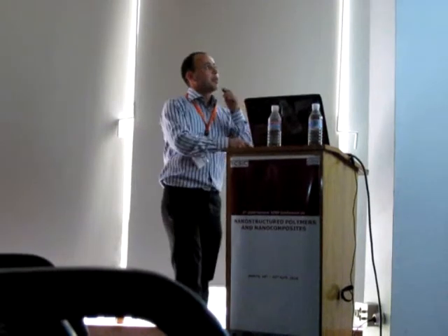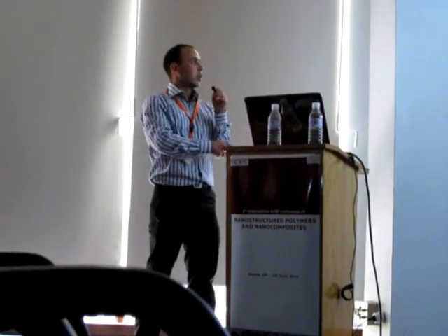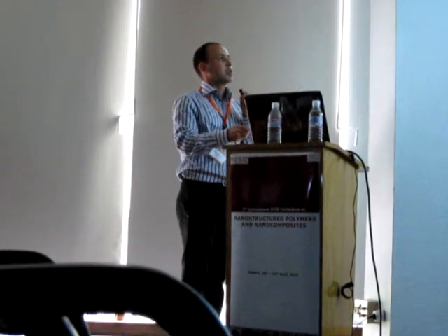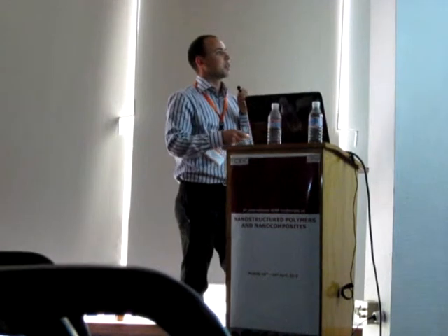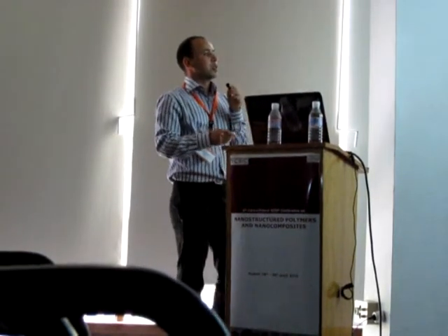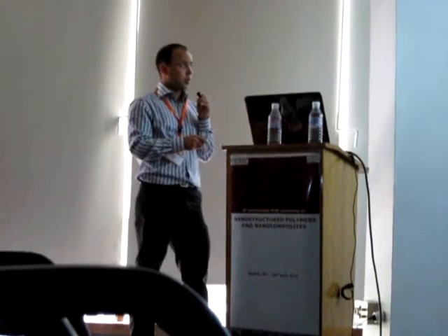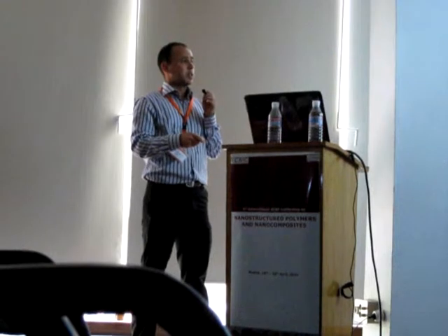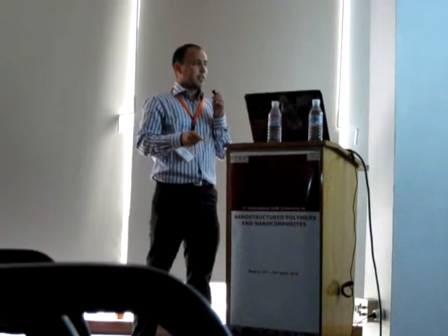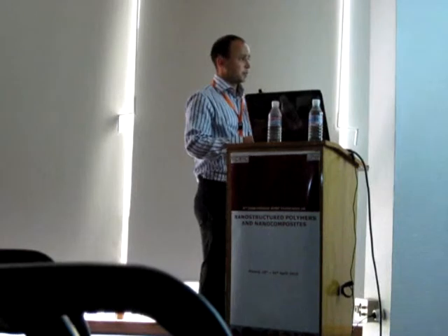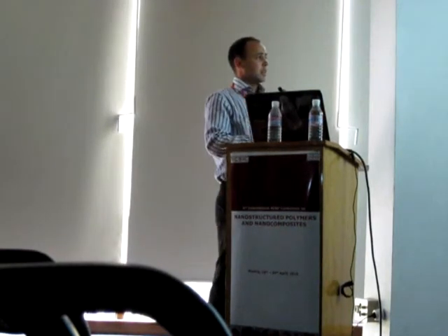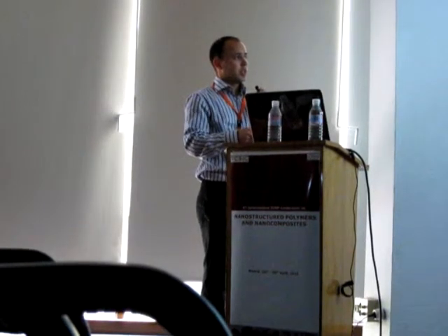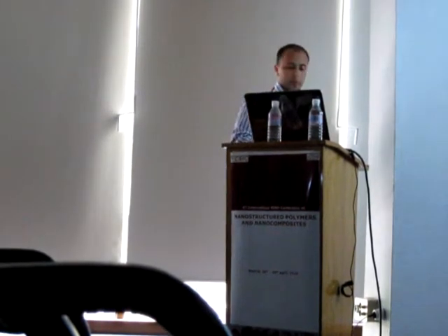Here also we present the conversion as a function of different process parameters, as a function of screw speed, feed rate, and different percent of precursor injected. To summarize, when percent of precursor increases, feed rate increases, and screw speed decreases, conversion rate decreases, and vice versa. To interpret these results, there are two factors: residence time and H factor. H is the initial hydrolysis ratio.